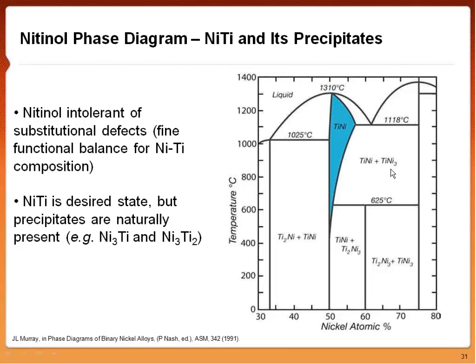So you can think of moving these precipitates in and out of your nitinol matrix. That'll change your transformation temperature based on the graph we saw before. Obviously, if we put a little bit more nickel in, we're going to lower our AF or our martensite start temperature, and if we let nickel out, we're going to raise our martensite start temperature and raise our austenite finish temperature. So we can do this by different types of heat treatment.